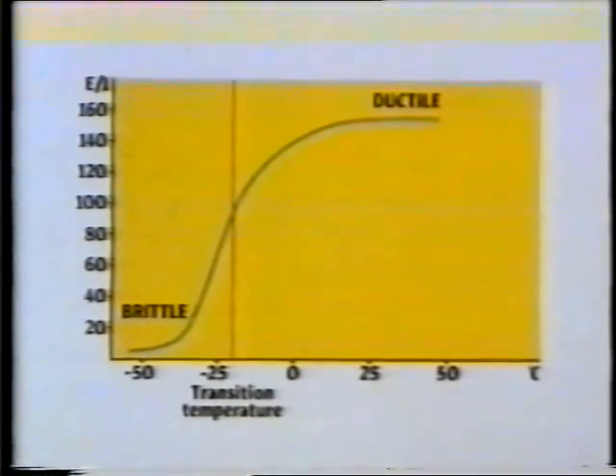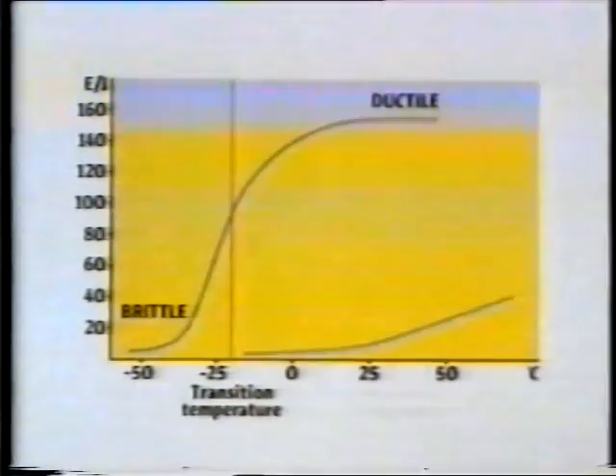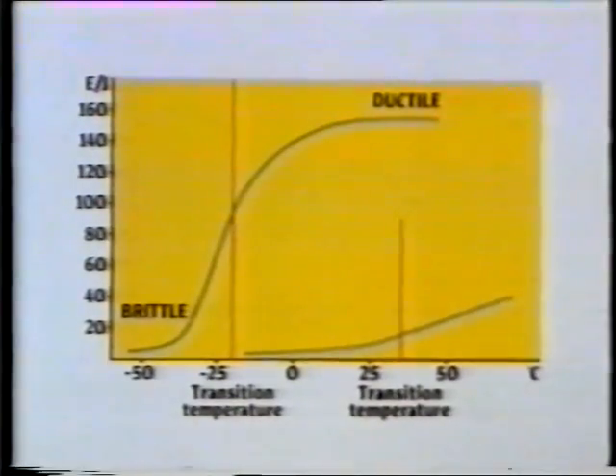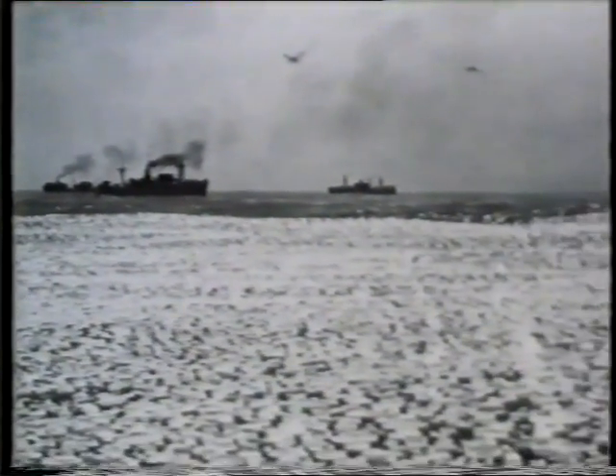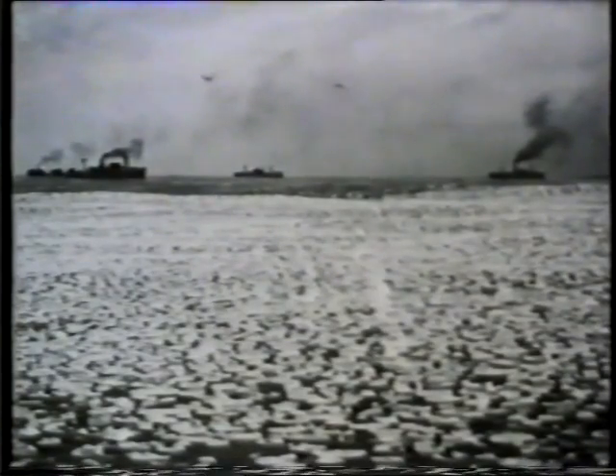This steel is of high quality and remains ductile to extremely low temperatures. But the steels used in Liberty ships were of much poorer quality. As a result, the transition temperature was rather high, sometimes above room temperature. Many of the failures of Liberty ships occurred in cold, even Arctic conditions, where the steel would have been on the lower shelf and consequently extremely brittle.